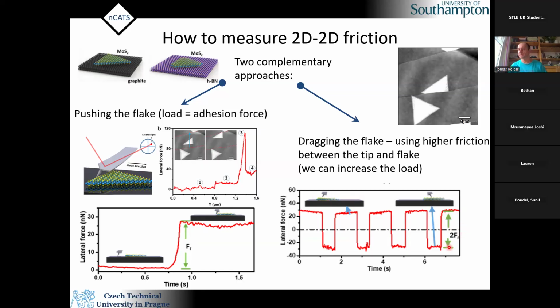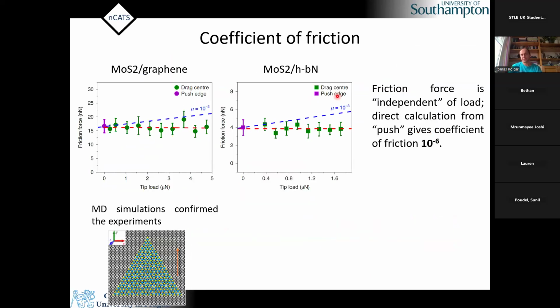And again, you measure the force. So we developed a new technique. In the movie, you see that we were able to move the flake, so it worked perfectly. And now we could measure friction. When we calculated the friction, we got a value of 10 to the minus 6. It's one millionth. So it's one of the lowest frictions ever measured for solids. And in fact, if you go a little bit more into detail, very likely the friction can be even lower than that. At least our simulations show that.